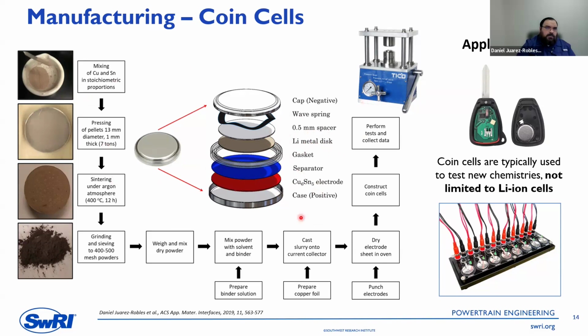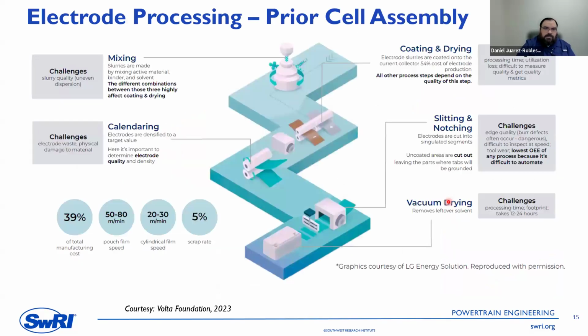Why this format is convenient is because, as I already mentioned, if you are testing a new chemistry and you want to see how it performs, you just prepare a small amount of that material, then you cast it in your electrode, you punch it, and you put it in your coin cell, and it's ready to test. If it doesn't work, you can dispose of it and prepare a new one. In some cases, you can prepare hundreds or thousands of these coin cells just to test a single chemistry. Now, this is just at the lab scale. At some point, once you're sure about your chemistry, you will move to a bigger format. And these applications are quite standardized, because the format of the cell is already standardized.